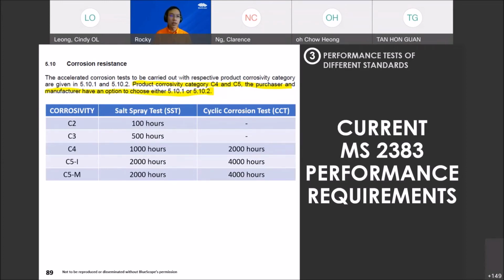So I just made a table for you to have a better imagination. If the product is to be classified as C2 and C3, it can be tested in salt spray test alone, because the environment itself is not as corrosive. Most often the salt spray test itself will show corroborating data with the outdoor exposure, but not always, mind you, because there are specs out there that are not even suitable, but can or might pass this salt spray test, again based on what we saw.